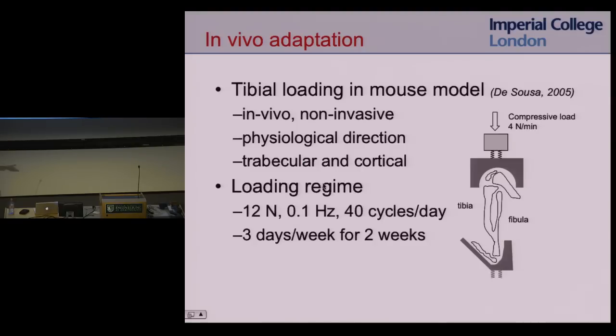So the loading regime is about 12 newtons, about 0.1 hertz for 40 cycles a day. So that's about 10 minutes of loading at 12 newtons, which is fairly big for a tiny little mouse, 3 days a week for 2 weeks. So that's six bouts of loading, 10 minutes of loading each, and we get significant bone growth. So you can actually measure the amount of bone growth in that leg.